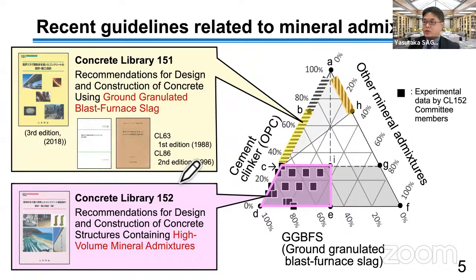This graph shows the ternary blending ratio of OPC, blast furnace slag, and other mineral admixtures. So point A is ordinary Portland cement, 100% cement clinker. The yellow line means slag cement, class B and class C. In other words, this area is the mixture of OPC and slag only. The orange line means fly ash cement.